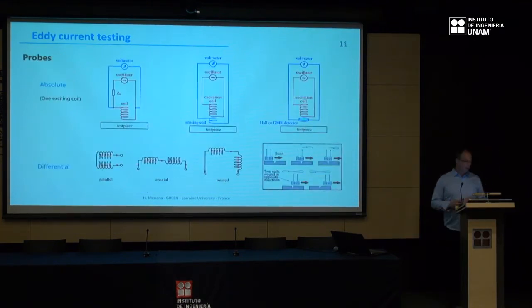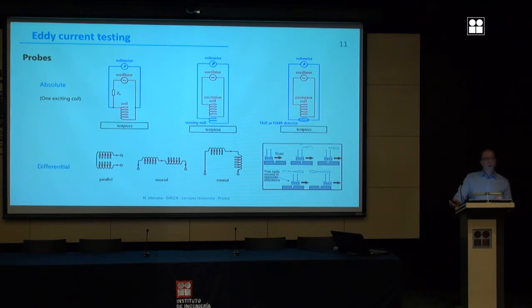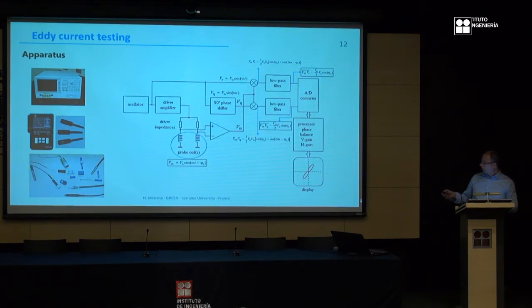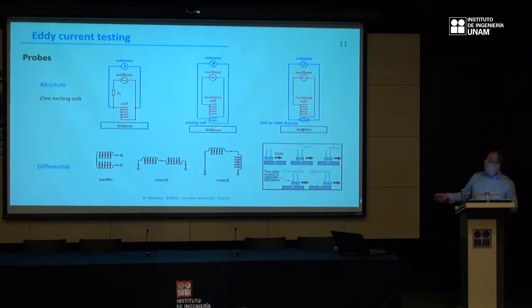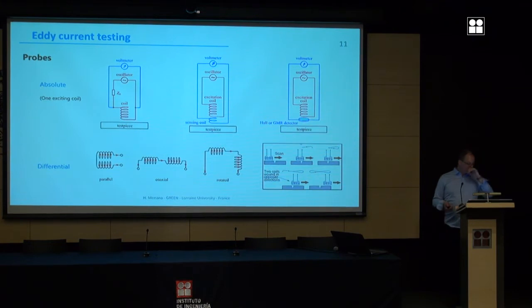We have two main configurations of probes, which we call absolute probes and differential probes. In the absolute probes, one coil is used for the excitation. One coil is fed by an alternating current. The same coil can be used to sense the result, or you can use a secondary coil for sensing, or you can measure directly the magnetic field instead of measuring the induced voltage on a coil to characterize the material. And in the differential probes, we have two coils wound in opposite directions.